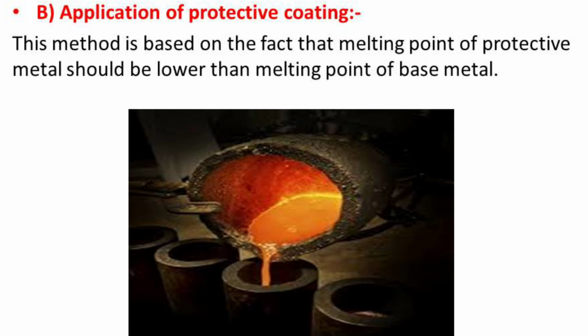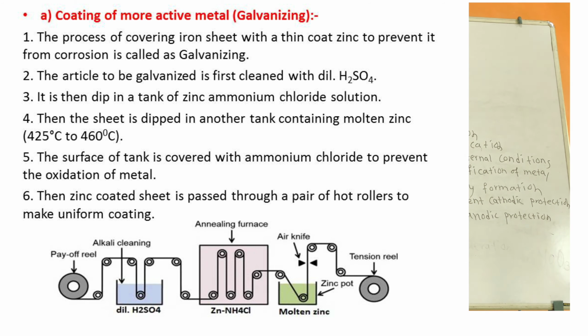Now the first method is galvanizing. It is the process of covering iron or steel sheet with a thin coat of zinc to prevent it from rusting. See the diagram. In this process, the steel article to be galvanized is first cleaned with dilute H2SO4 to remove impurities and oxide layer. Then it is dipped in a bath of zinc ammonium chloride solution and allowed to dry. The sheet is then dipped in another bath containing molten zinc at a temperature of 425 to 460. The surface of the bath is kept covered with a flux of ammonium chloride to prevent oxide formation.